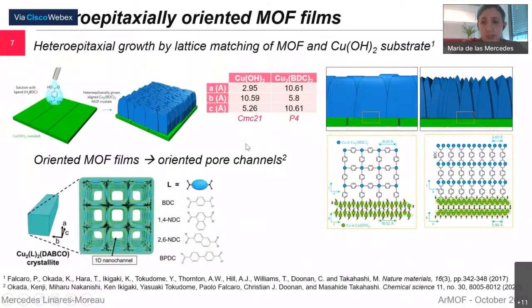So by ensuring the lattice matching, by selecting a ligand and a MOF that has a crystal structure that is compatible with the crystal structure of the copper hydroxide, it is possible to grow MOFs that are macroscopically oriented. This has been extended to other linkers and other MOFs, in this case copper-based, of course, because we are using the copper hydroxide as a source for the metal cations. But it's interesting because in this way you can have oriented pore channels, which could be interesting for several